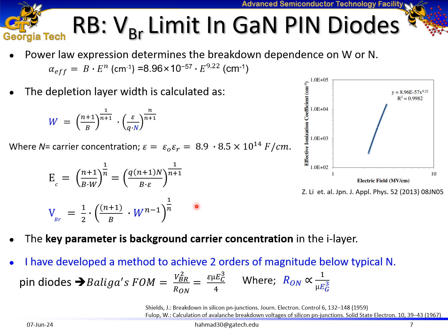In this slide, I have shown the physics leading to the calculation of the breakdown performance of gallium nitride based pin diodes, which is dependent on the achievable depletion layer width, and that is further proportional to the background carrier concentration in the I layer of a pin diode. So the lower the background carrier concentration in the I layer of a pin diode, the higher the breakdown performance of pin diodes would be. And this is a key parameter. I'm going to show it later, but I have developed a method to achieve 2 orders of magnitude below the typical carrier concentration in gallium nitride pin diodes.